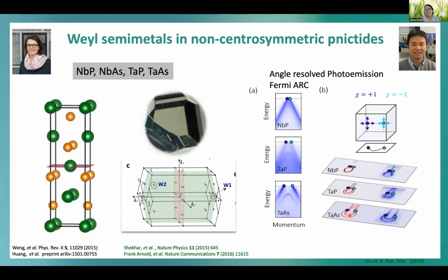And here you see the calculation of the Fermi arc and the measurement of the Fermi arc, and this was quite convincing - people now really believe that this material is a Weyl semimetal with Fermi arcs at the surface.